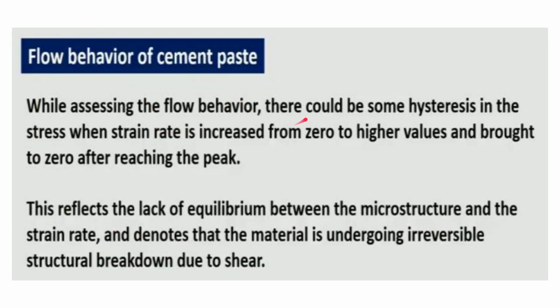While assessing the flow behavior, there could be some hysteresis in the stress when strain rate is increased from 0 to higher values and brought back to 0 after reaching the peak. This reflects the lack of equilibrium between the microstructure and strain rate, and denotes that the material is undergoing irreversible structural breakdown due to shear. Because of this hysteresis behavior, the material is not coming back to its original shape, and that means some irreversible structural breakdown might have occurred because of the presence of shear. That is the reason why the hysteresis occurs.